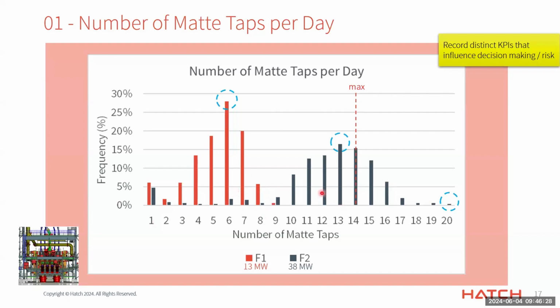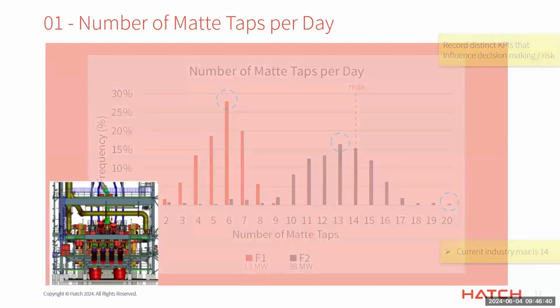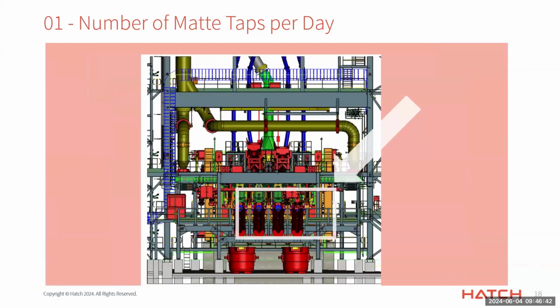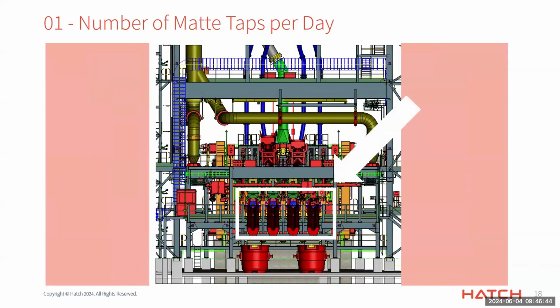You'll see the number of maximum taps per day that furnace 2 can achieve is at a high of 20. Very, very high, exceeding the current industry max at 14. So given the results of the model, we were then able to validate the design of the furnace of 4 mat tap holes with the aim of reducing tap hole and launder wear.